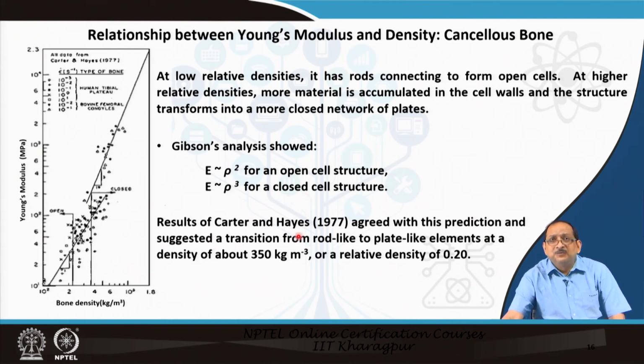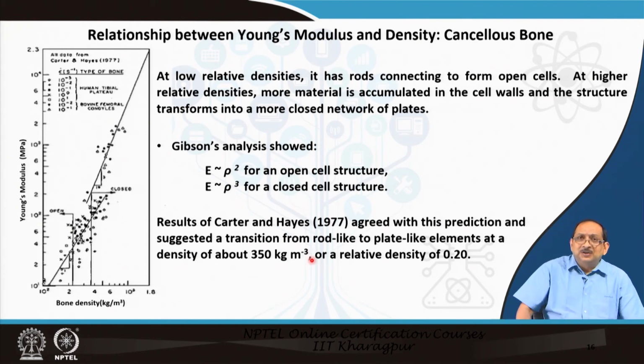So, the experimental results of Carter and Hayes agreed with this prediction and suggested a transition from rod-like structure to plate-like structure at an apparent density of about 350 kg per meter cube, or a relative density of 0.2. Now, let us consider